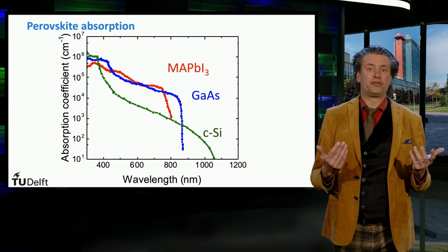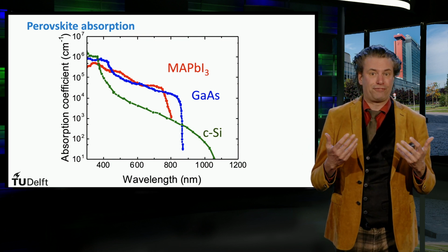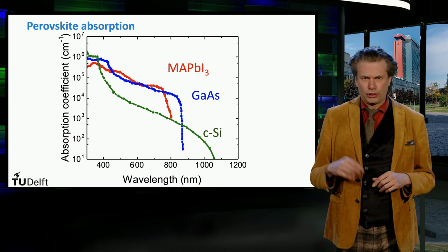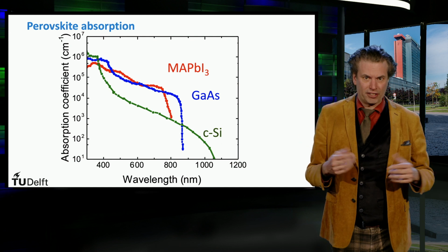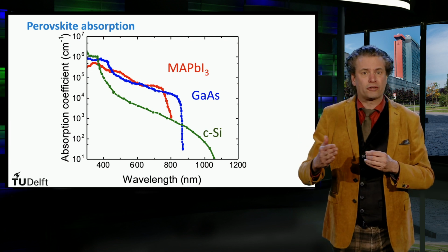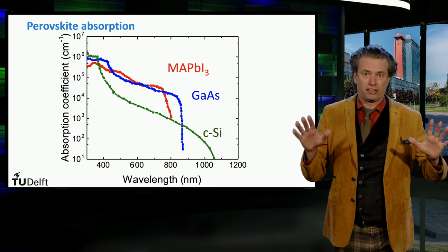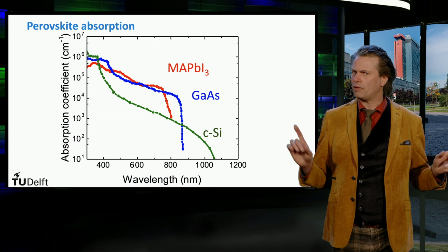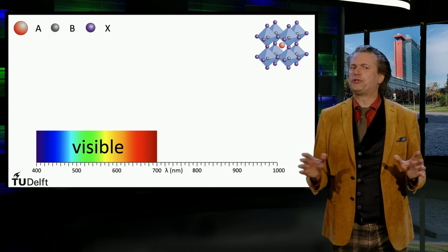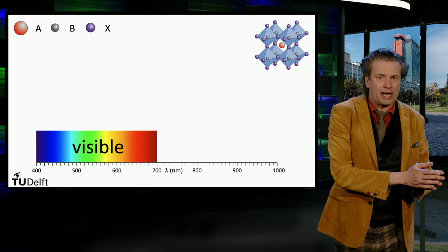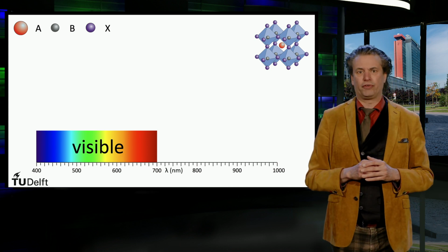The perovskite material does not have a field-dependent exciton dissociation. Also, due to its defect tolerance, the low trap densities in the bulk result in a long intrinsic diffusion length and relatively long carrier recombination lifetimes. The band gap can be tuned by the alloy and can range from 1.3 electron volts up to 2.3 electron volts.